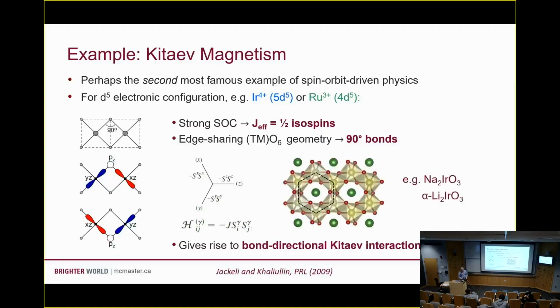And when you put these onto real lattices, like the honeycomb lattice here, which is a nice edge-sharing octahedral crystal structure, then with the strong spin-orbit coupling and this bond geometry, you can get these directional Ising interactions that can give you what we call a Kitaev magnet, or in some cases a Kitaev quantum spin liquid.